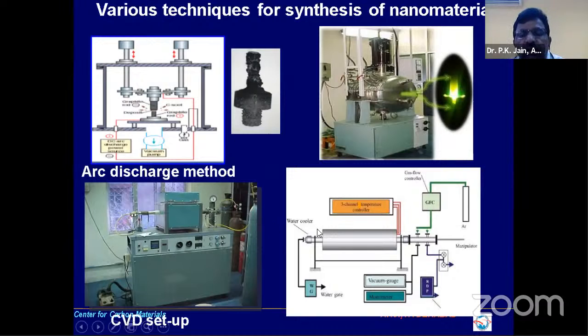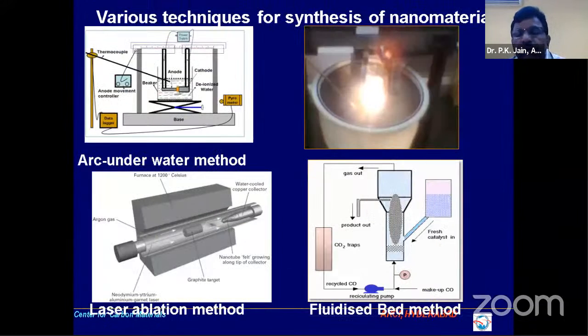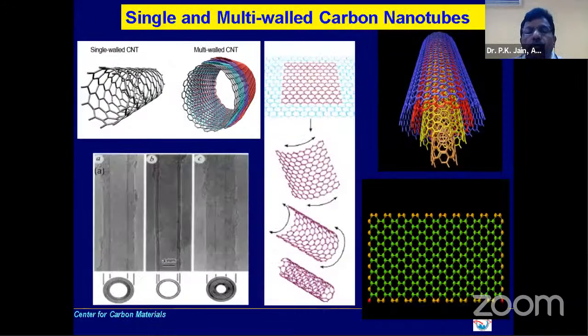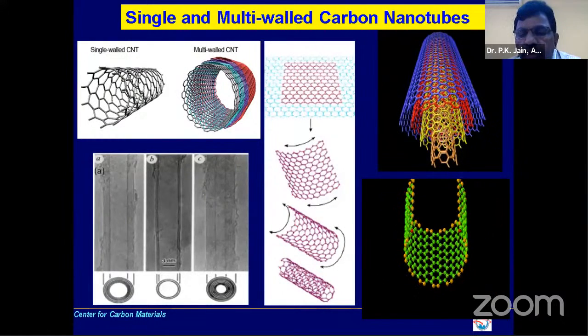Now there is another called CVD, chemical vapor deposition. You take a normal furnace and pass a hydrocarbon gas, and at high temperature you can deposit the carbon nanotubes. Apart from that, we also have the arc underwater setup. This is the laser ablation and the fluidized bed reactor. This is for continuous production. Now people are anyway aware of that.